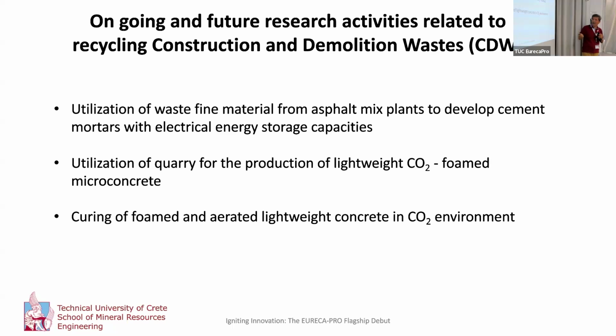Also, we are working on another direction, which is to use these fine quarry byproducts for the production of lightweight concrete, but not using the common foams that are used for this, but using a foam which is made from carbon dioxide and special chemical additives. And also, we are working on curing this cementitious material in a carbon dioxide environment instead of water. This means that the curing is shorter, and we also have a lot of environmental benefits because it absorbs carbon dioxide from the atmosphere.